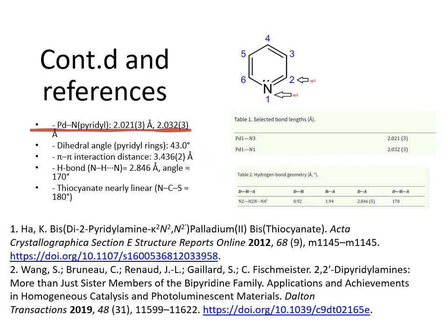Hydrogen bonding was observed in the nitrogen-hydrogen-nitrogen interactions with a donor-acceptor distance of 2.846 angstrom and an angle of 170 degrees, which helps stabilize the crystal packing. And pi-pi stacking interactions were also observed between pyridine rings with a distance of 3.436 angstrom. These measurements help provide a better understanding of the structure's complex geometry and bonding through X-ray diffraction.